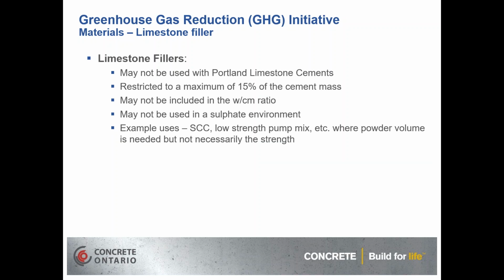There's a restriction that with the limestone filler, if you're using it, it can only be included up to a maximum of 15% of the cement mass. The other thing we have to consider is that it may not be used in the calculation for the water to cementitious materials ratio, and it may also not be used in a sulfate environment. So some example uses where the limestone fillers really shine is where you're looking at stuff like self-consolidating concrete mixes or a low-strength pump mix, etc., where you need some powder volume in there to modify and enhance the rheology of the concrete, but you might not necessarily need the strength that would come along with going with an overly high cement content in the mix.